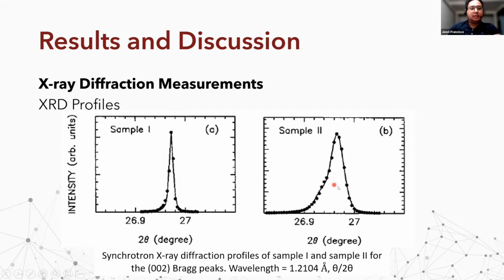Visually, we can see it. The dots here represent the experimental data, plotted, and the solid lines are the least squares fits using the pseudo-Voigt function. Sample 1 employs a single peak fit, while sample 2 employs a two-peak fit due to the presence of a broad shoulder. As we can see here in the peak of sample 2, we have a shouldering. We can imagine it as two peaks superimposed within each other: the first peak, the broader one, and the narrower peak. The two-peak fit method was employed to determine the peak width of sample 2.